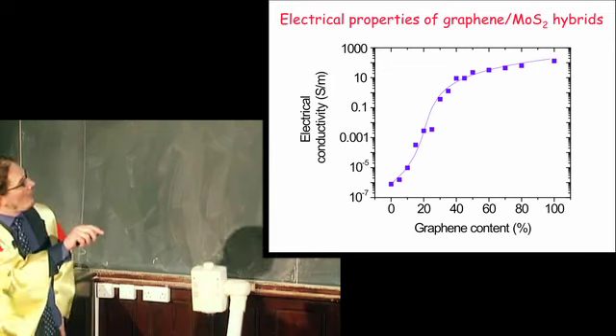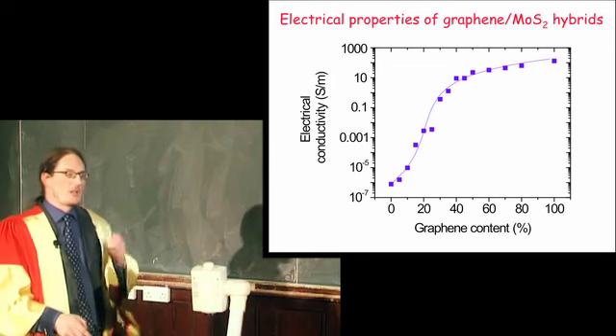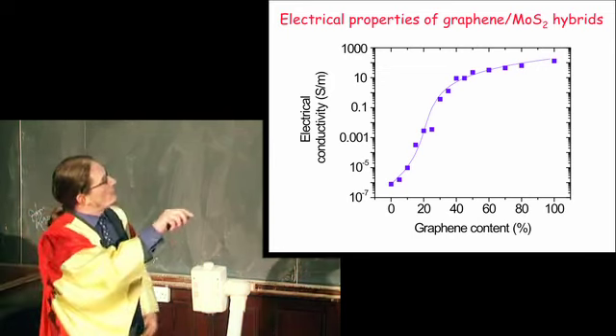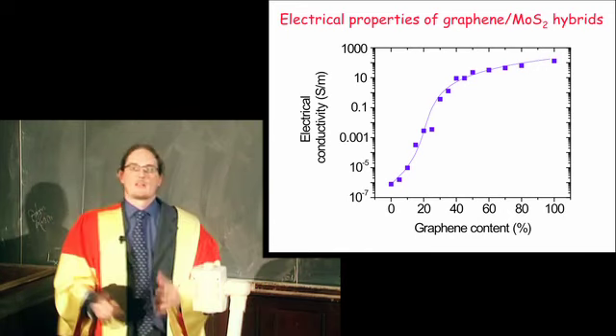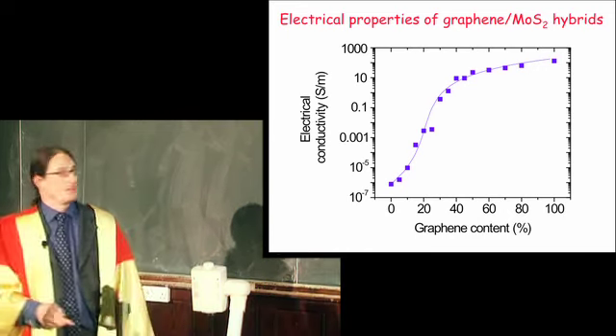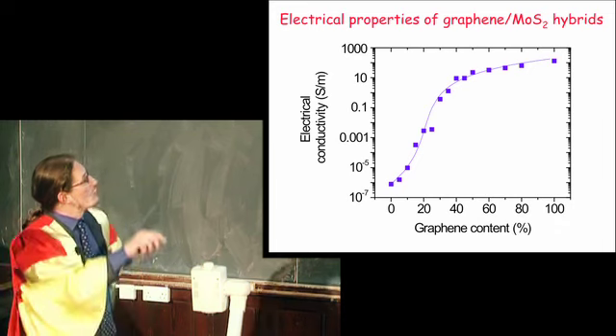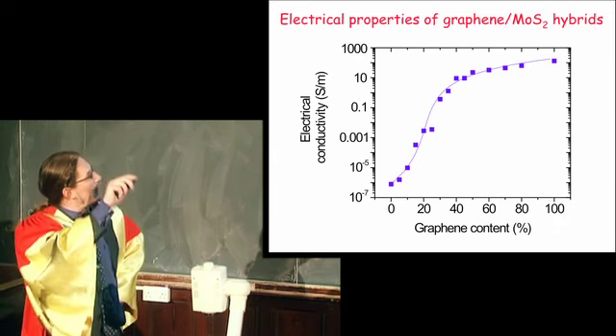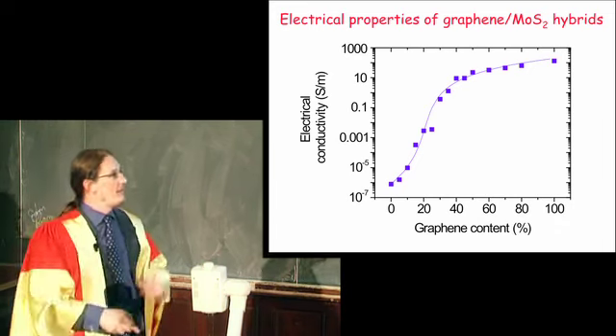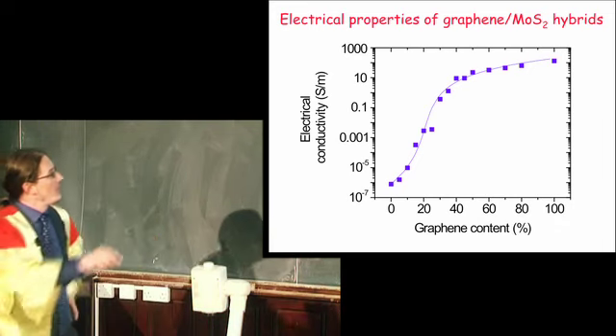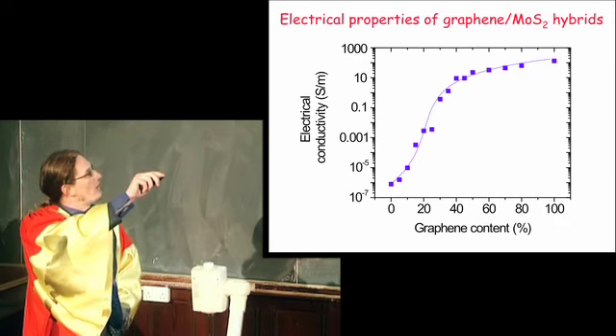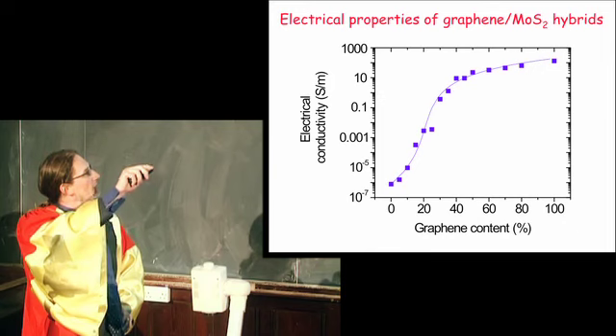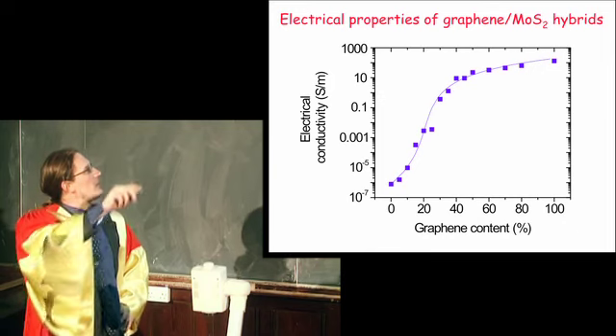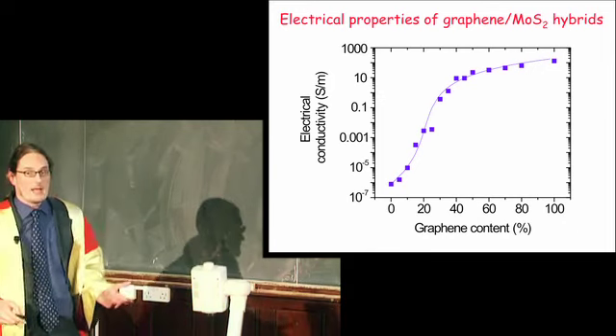But graphene and carbon nanotubes are conductors. So if you put conductors into these materials, then you might increase the conductivity. And in fact, you do. This is a graph of the electrical conductivity as a function of the amount of graphene that we've put into these composites. And you can see the conductivity increases dramatically from a very, very low level by, I don't know, what is it, 8 orders of magnitude.